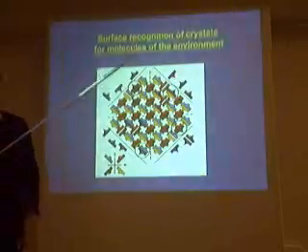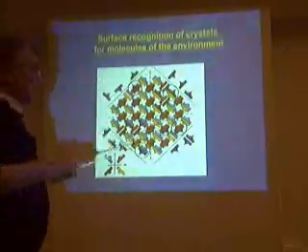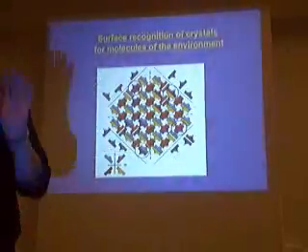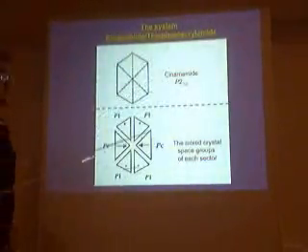So in other words, if you grow a centrosymmetrical crystal in the presence of another molecule, you are going to get a hybrid structure composed of different crystals, of different space groups. And these space groups will be lower than that of the bulk crystal. They will be determined by the structure of the surface through which this molecule has entered that particular sector. Okay? And we've done an experiment of this kind. We've taken cinnamide as a molecule which is non-chiral.